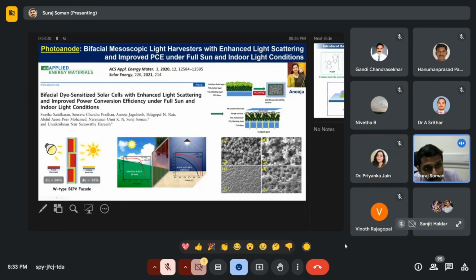But the issue here is that you want to make a solar cell which is semi-transparent, a see-through solar cell which you can use for building integrated photovoltaic facade applications. There, when you use a larger nanoparticle, even though you get better scattering, that hinders your transparency. You are losing your transparency. Automatically your solar cell will become opaque. So there, we have done a very interesting work.